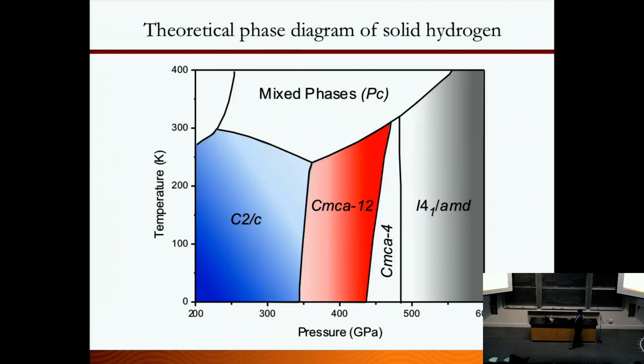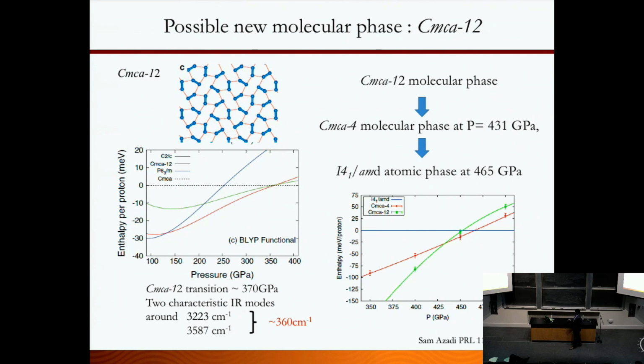Clear indication of a phase transition. So to understand this one, what kind of phase is this one? We look into the theory, and this is the theoretical phase diagram they have predicted. They predicted somewhere around 340 GPa or 370 GPa, there can be a new phase transition. So this is the enthalpy studied. They come up with around 370 GPa.